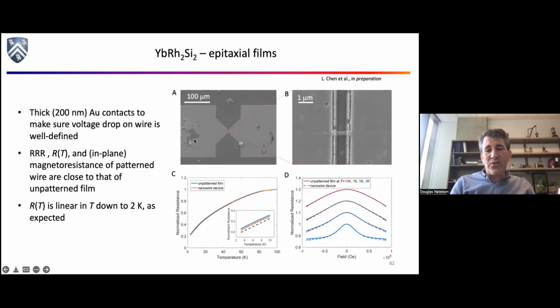So here, this looks a little torn up because that's where the leads were bonded on. But if you zoom in, here's that little snippet of wire between two big pads, okay? And how do we know we didn't ruin the material? Well, we can compare the properties of this device, which is basically in red here, as a function of temperature. This is resistance versus temperature. We can compare it with an unpatterned film. And what you find is that if you normalize everything to say 100 Kelvin, they look basically the same.